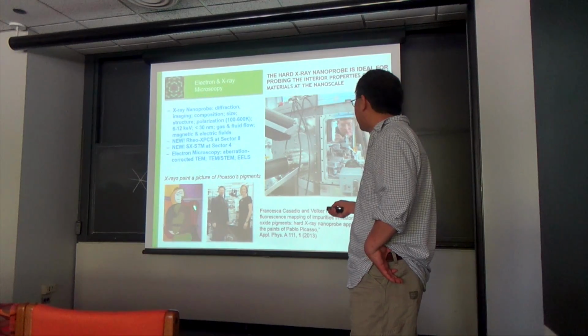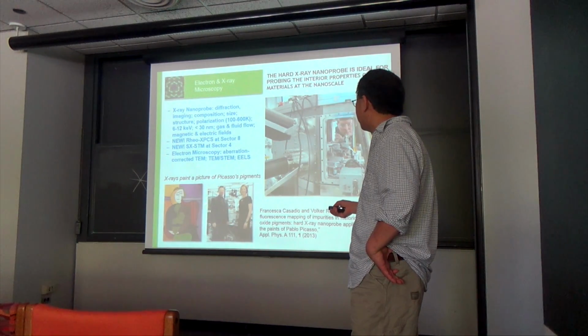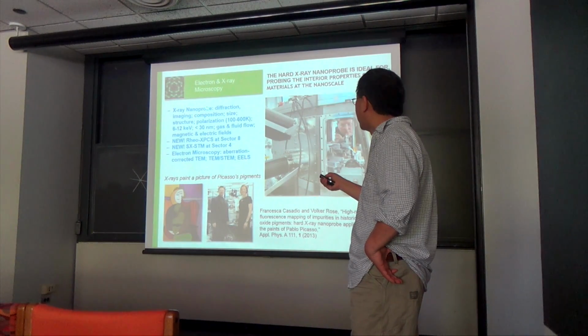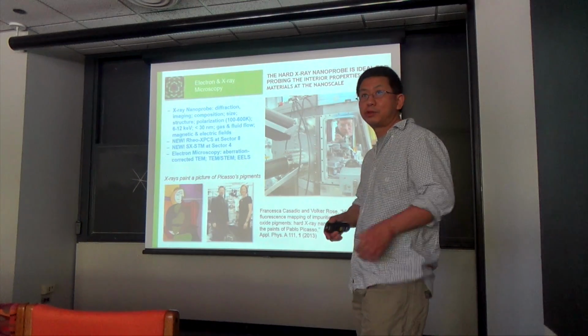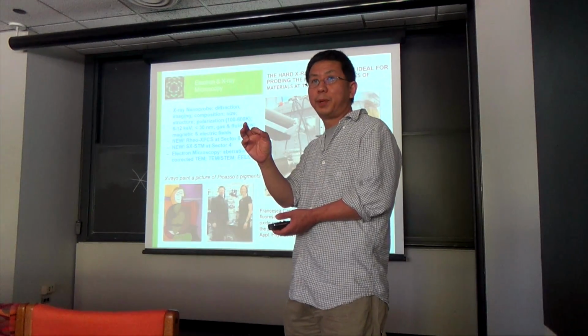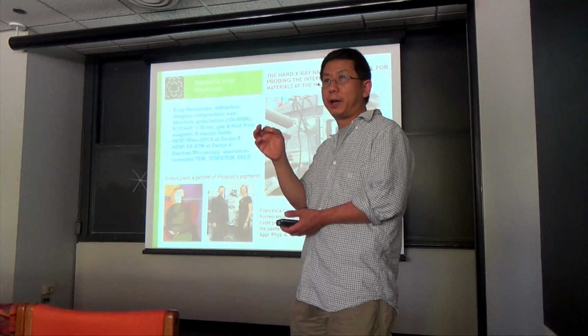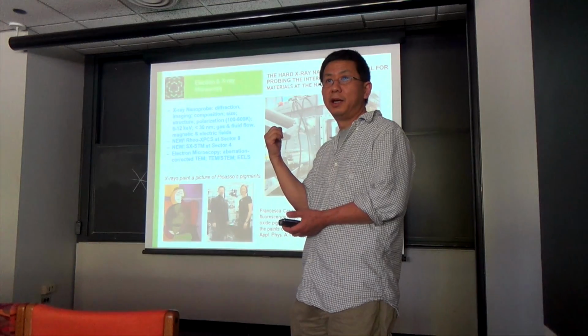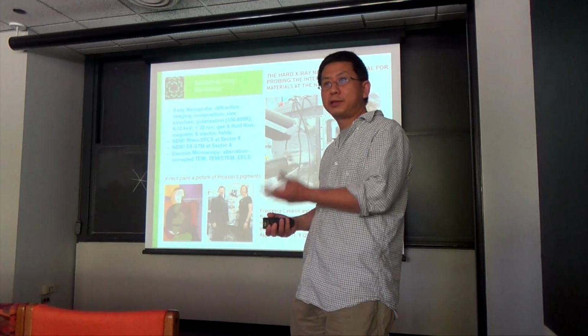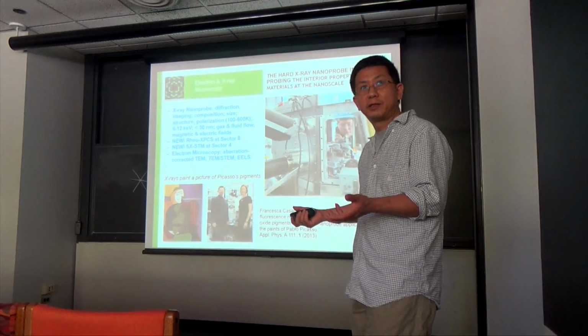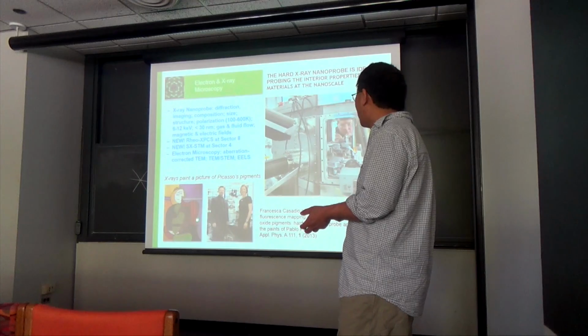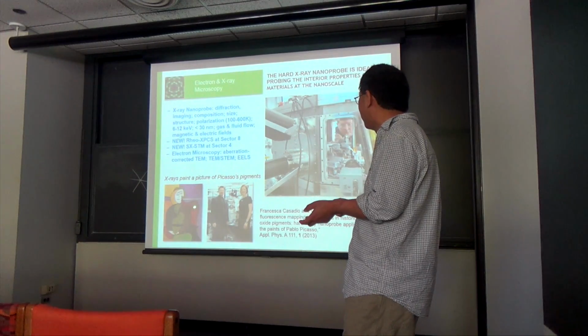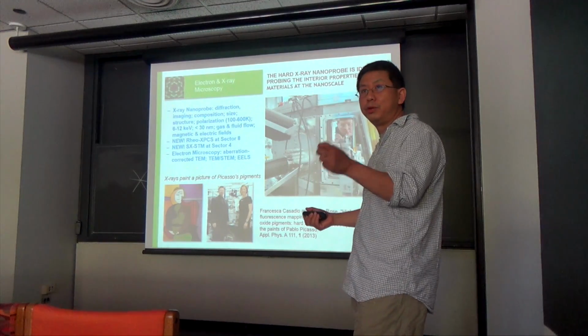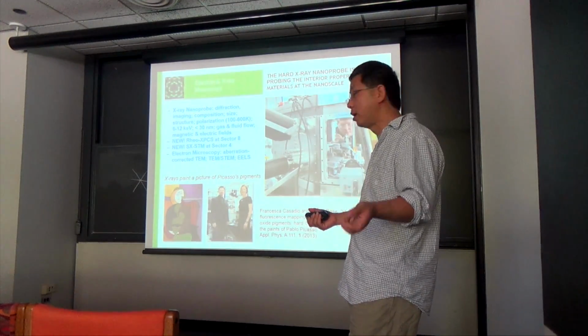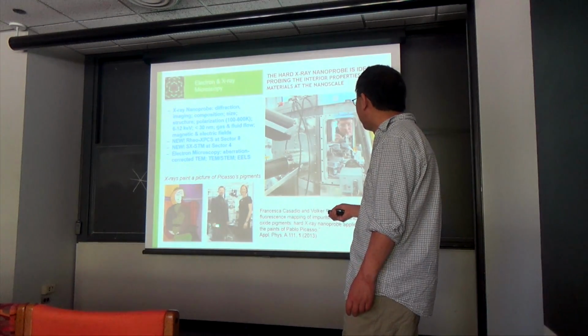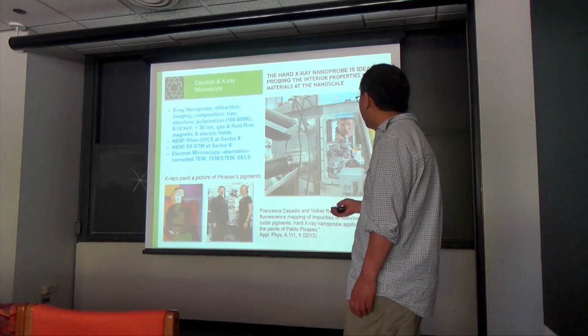Now, one famous example that was done at Argonne is using this X-ray nanoprobe to look at Picasso's pigments. Essentially, you can scan a very small sample of the pigment and find out what kind of elements are in the paint that Picasso used in his painting, right? So it's actually one of the best ways, as far as I know, to detect counterfeits. Because if you try to fabricate a new painting as a counterfeit, a fake one, the paint material you use today is very different from the paint material used in 1800 or 1900. So that is the best way to find out what is real or not real of the Picasso painting.